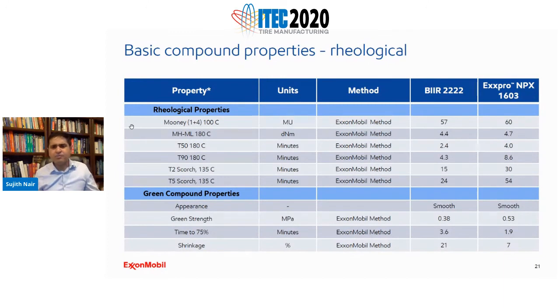Just looking at compound properties in general, rheological properties, if you look at the Mooney, it's very similar. Exxpro probably has a slightly higher Mooney than bromobutyl because the inherent Mooney of Exxpro is around 2 to 3 points higher than that of bromobutyl. So you're going to see that in your compounds as well. Plus, you've got this good reinforcement between the filler and the polymer, and that adds a little bit of Mooney as well. But there are multiple ways to reduce this Mooney and make it equal.